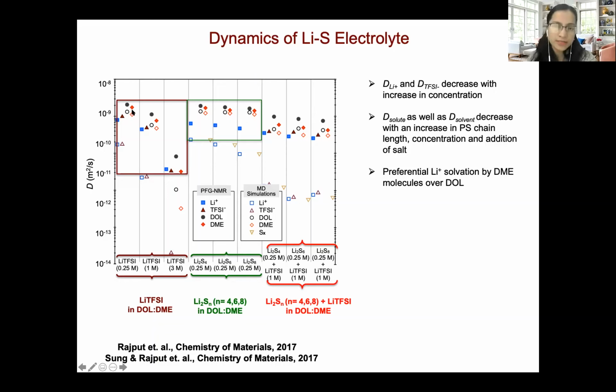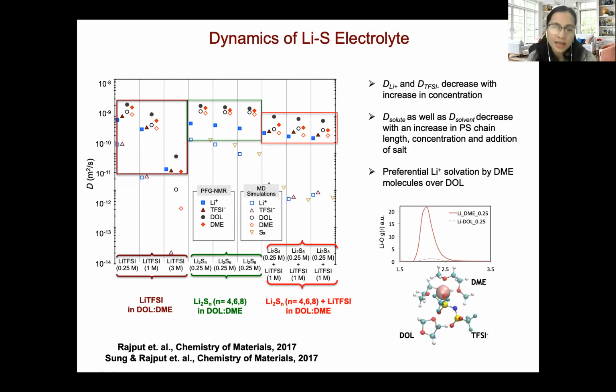Okay, they both have very similar physical and chemical properties. They both have the same dielectric constant of approximately 7. But it was interesting to see that consistently one of the solvent is moving faster than the other. And we learned that that's happening because of preferential solvation of DME solvent over DOL molecule. And that's because of the geometry of DME molecule, which has the linear geometry, and it can bind through its oxygen atoms, compared to DOL molecule, which has the cyclic geometry, and doesn't bind that strongly with lithium ion. And because of that, DME molecules is kind of diffusing along with lithium ions, which makes its diffusion slower compared to DOL solvent. Okay, so the geometry of the solvent is also an important parameter to take into consideration.